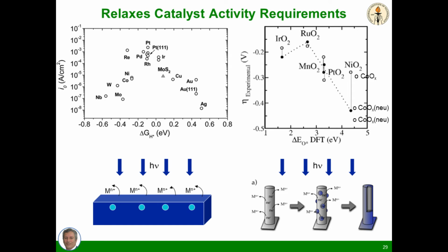This leads to a factor of 100 decrease in the catalyst turnover for a microwire array as a requirement relative to a planar sample. In addition, for a fuel cell or an electrocatalyst that's working in an electrolysis system, the current density demands are in the order of 1 amp per centimeter squared, whereas they're 100-fold less, 10 milliamps per centimeter squared, for the solar photon flux. Those two factors of 100 relax the catalyst activity requirements so that we need not have as active catalysts for the hydrogen evolution reaction to be kinetically competent in the solar fuel system as we would in other applications.